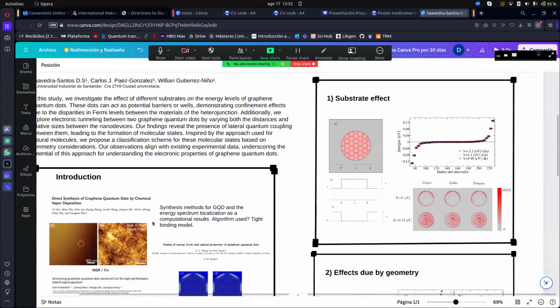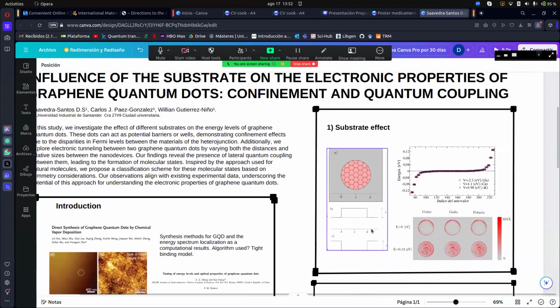Well, as the first part of the study, we are focused on examining the effect of different substrates on graphene and how they influence its energy levels. The primary idea was to investigate two different types of potential behaviors, barrier and well, as the figure shows. The three materials used were copper, gallium, and potassium, with the potential barrier formed by the difference in Fermi energies between graphene and the substrates. This study was conducted on a circular graphene quantum dot with a radius of 40 nanometers.